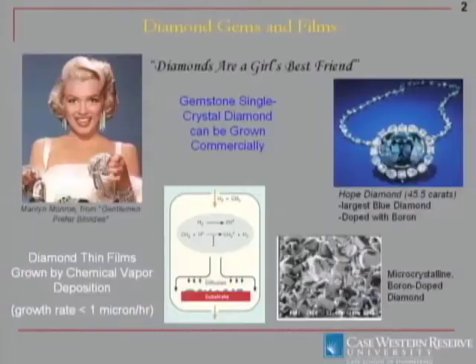Our growth rates are much slower, so there's no way that I can grow a very large diamond. It would take me months to grow something large enough that you could hold in your hand, the equivalent of something that would go into a ring, and it may not look that good at that point. Here's an example of a polycrystalline film. This is microcrystalline because the grain size is on the order of microns. And this particular film is a boron-doped film, which under a microscope doesn't really look any different. If you were to grow it single crystal, it would look blue because of the boron in that lattice.